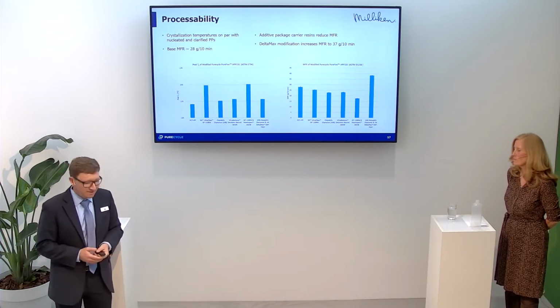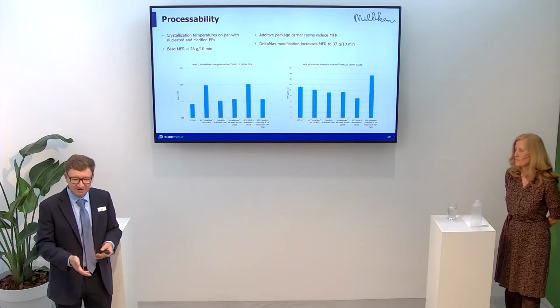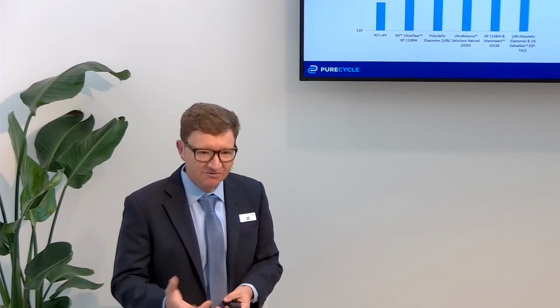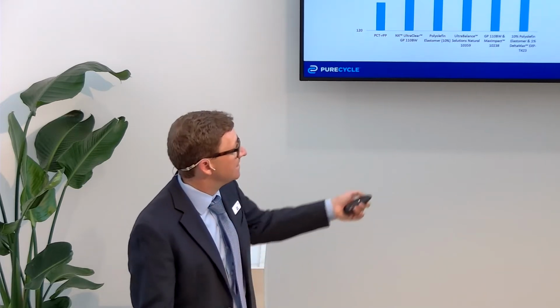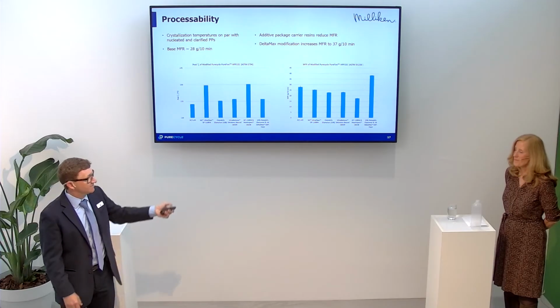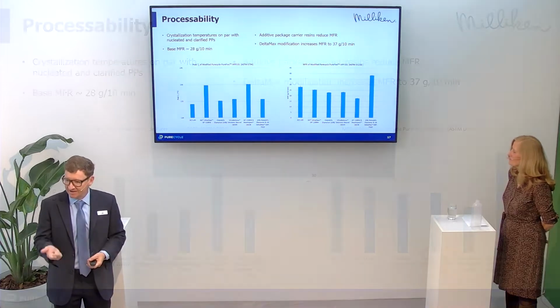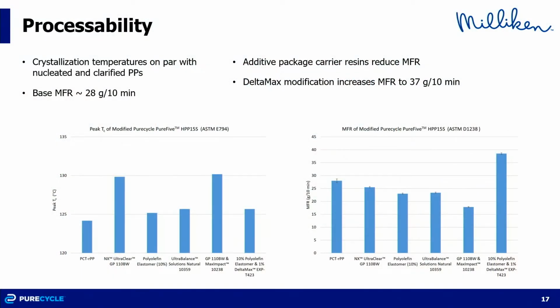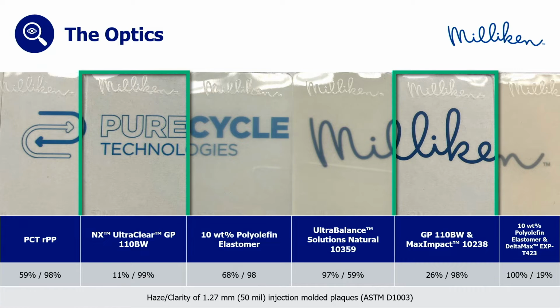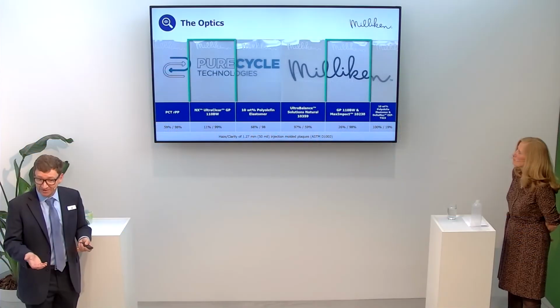But I know when PureCycle starts scaling up, they'll have a nucleated package and then also a clarifier package most likely. So those materials will be 100% post-consumer content. They won't have the master batch carrier. And then finally, our Delta Max, which is designed to increase flow and impact, got us up to about a 37 melt flow.